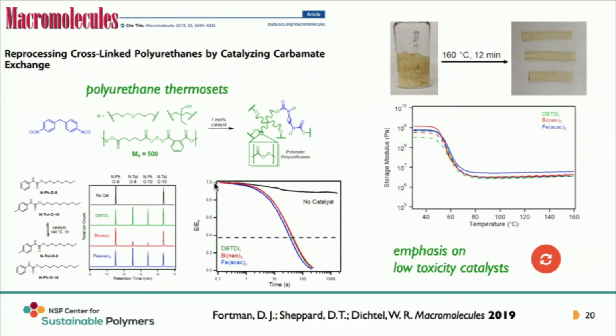And what you're seeing here is what's called a stress relaxation experiment, which is evidence for reprocessability of a thermoset polyurethane. In the absence of catalyst, you don't see it, and in the presence of catalyst, you do. The storage modulus of these materials actually after processing remains quite the same as the original materials, and there's emphasis on low toxicity in the catalysis. So here's an example of how a ground up polyurethane can be reprocessed into similar type materials.